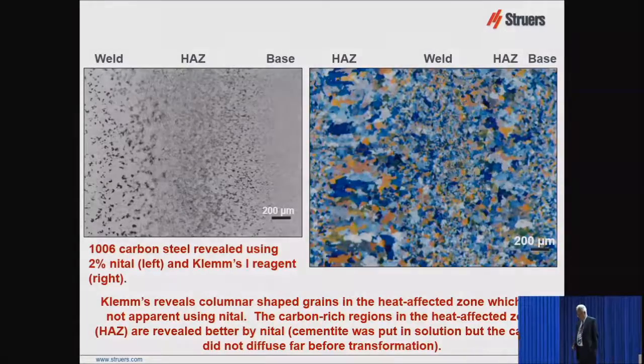Here is an etch of 1006 carbon steel, a welded sample. The weld metal is over here. This is the heat affected zone. Here's the base metal. Now, when you look at it etched with Klemm's reagent, you can't see the pearlite that's in here, but you're seeing the ferrite grains beautifully, because Klemm's is the most powerful colorer of ferrite in steels. No etch is as powerful.